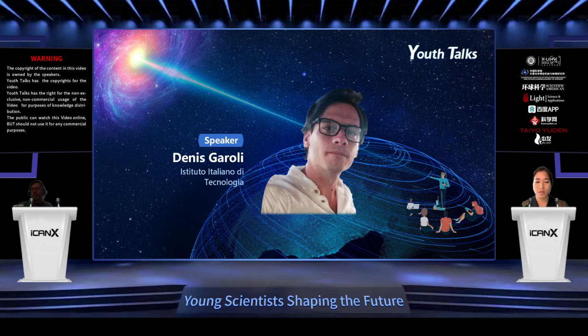Mm-hmm. And regarding the trapping, how challenging is it to trap the molecule? Because also, I guess you have to have a low concentration so you can trap one molecule. And so are you diffusion limited to put it in the right place? No, to trap a molecule is quite challenging, in a narrow cavity, so in the case of a nanopore, a very narrow nanopore. It could be quite challenging. The approach we are using is to attach the molecule to a nanoparticle, and to trap a nanoparticle is pretty easy. A dielectric nanoparticle, a metallic nanoparticle can be trapped in a nanopore in a pretty easy way.